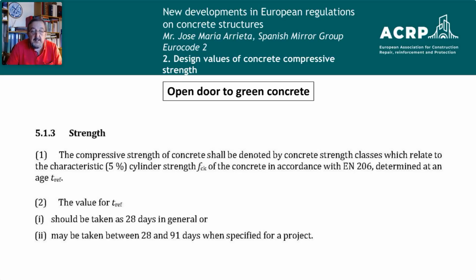The first thing is that this revision leaves the door open to allowing ages for the test higher than 28 days. Green concretes are produced replacing a portion of cement by a binder like fly ashes, for example. These concretes develop strength slowly, and it's necessary to test the specimens at a higher age. So this is why now t_ref may be between 28 days and 91 days for this case.